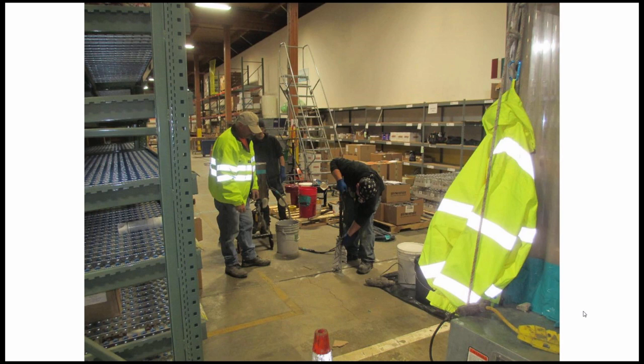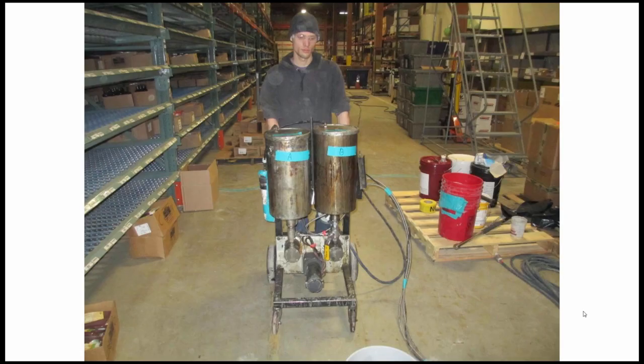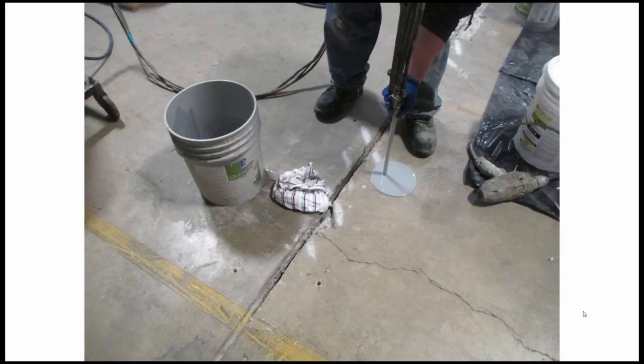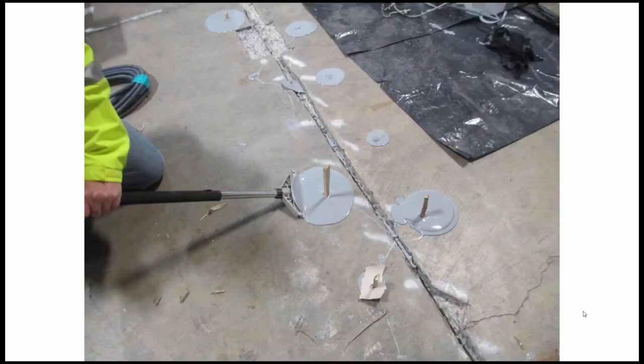And so here's an example of some guys pumping in, in this case, a polyurea filler material. And here's a guy with a pump, it's a low pressure injection pump. He's got a two-part material. You can see he's got the A and the B there. And here's a guy, again, pumping it in. You can see that they drill ports in the slab and pump it in. It's kind of like crack injection. You pump it in until it comes out the next hole. And once it comes out the next hole, you plug that hole that you're pumping in.